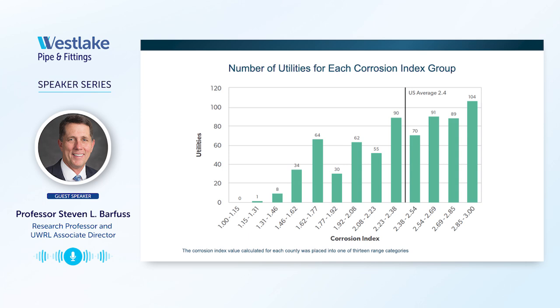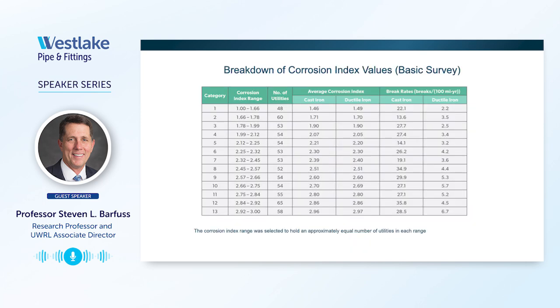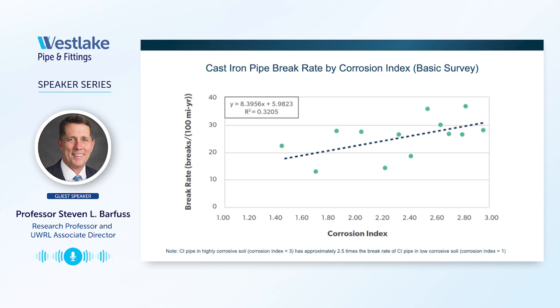But we can't analyze the data very well if the number of respondents is not equal. So we weighted the data by making an approximately equal number of utilities by changing the range of the corrosion index range. And then we looked at cast iron and ductile iron in terms of their overall corrosion index, and cast iron and ductile iron in terms of their break rates for those number of utilities. And then we plotted it. So now we have a weighted sample set, each dot representing approximately the same number of utilities. And you can see a trend.